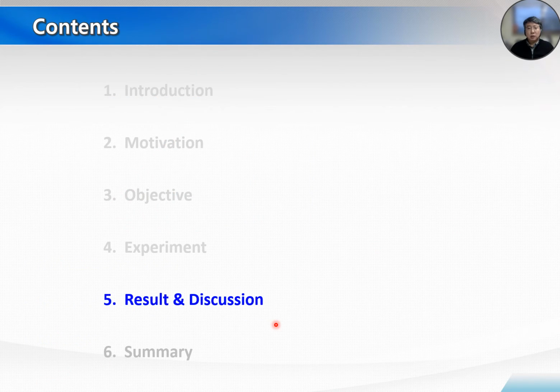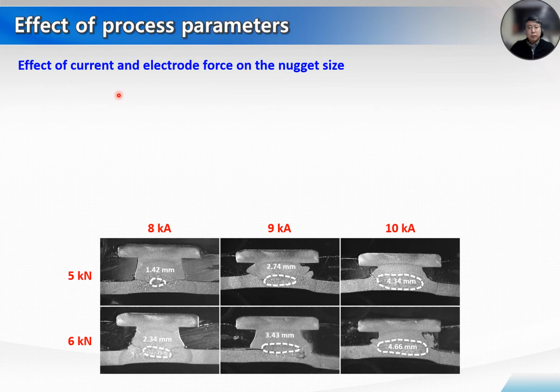The next are the results and discussion of this research. This slide explains the effect of current and electrode force on nugget size or welding quality of the one-step resistance element welding. With the pressing force of 5 kilonewton or 6 kilonewton, when we increase the welding current, it gradually increases the nugget diameter between the element and steel sheet. When the welding current was increased from 8 kiloampere to 10 kiloampere at 5 kilonewton and 6 kilonewton pressing force,